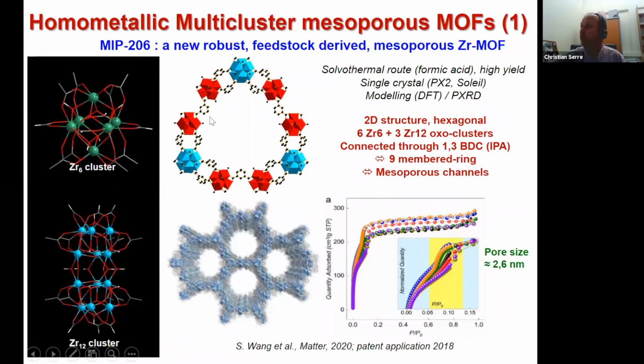It is delimited by 6 Zr6 clusters and 3 Zr12 clusters connected through the isophthalate. So it forms a nice 9-member ring. Therefore, the pore size estimated from the precise structure, and the pore size distribution by nitrogen porosimetry, is near 2.6 nanometers. So it lies in the mesoporous range.